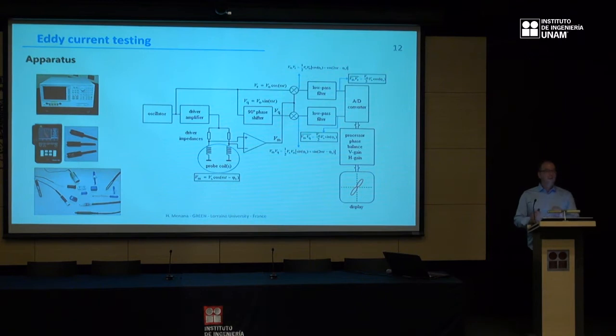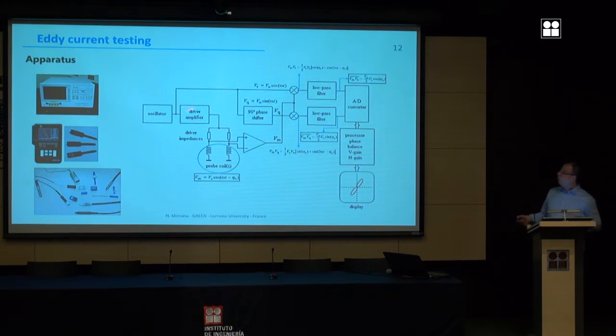The apparatus you can find is an experimental apparatus. It's a simple impedance analyzer, since we are interested in variation of the impedance of the test coil, or an industrial portable apparatus. We have different types of probes in geometry and size, from sub-millimeter to centimeter. The detection is based on synchronous detection to get the active and reactive parts. You have an oscillator that creates the frequency, the basis signal of excitation, which is amplified to feed the sensor.